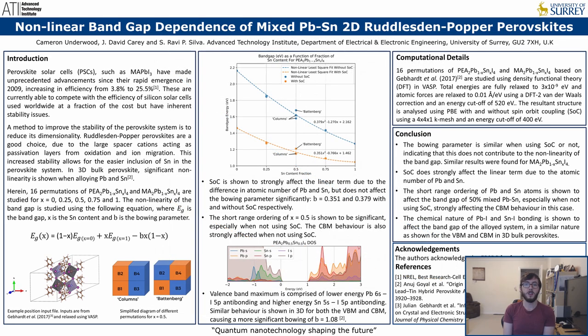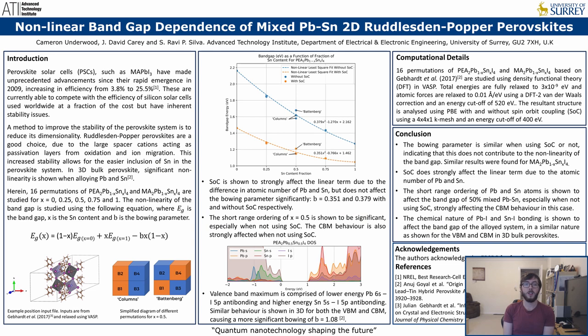To understand this further, we took a look at the chemical behavior at the band edges, and found that as we increased tin content, the conduction band minimum was shared evenly between lead and tin. But we found that the valence band maximum becomes dominated by the tin-5s / iodine-5p antibonding interaction, where the equivalent lead-iodine antibonding is lower in energy. This is very similar to the behavior observed in 3D bulk perovskites, except in a 3D material this competition in energy occurs in both the valence band maximum and the conduction band minimum, resulting in an even stronger bowing constant.